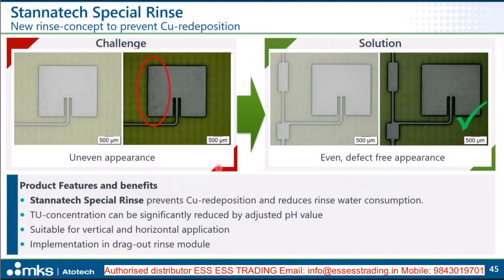And finally, that brings me to the post-treatment solutions that I would briefly like to introduce, starting with the rinsing. We talked a lot about rinsing because rinsing is really one of the key steps in the whole immersion tin process, simply because of the viscosity of the tin solution. And there are different rinsing concepts already in place. What we recently introduced is a so-called Stannatech special rinse. This is an additive which is added to the rinse after the immersion tin process, and the target for this rinse is to prevent copper redeposition and also to reduce the rinse water consumption.